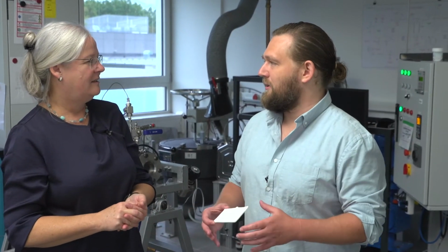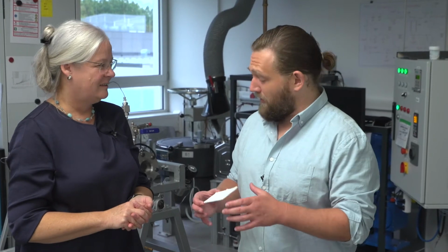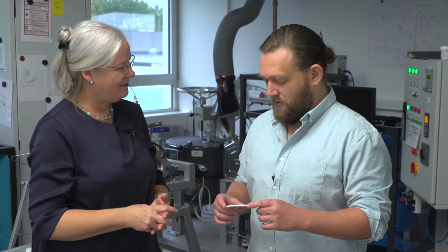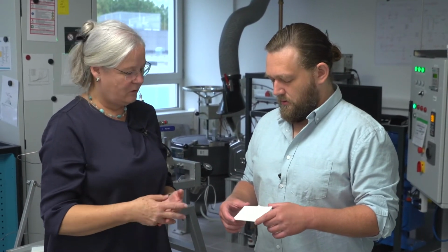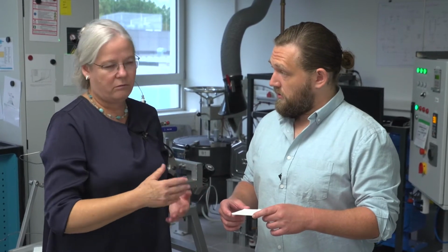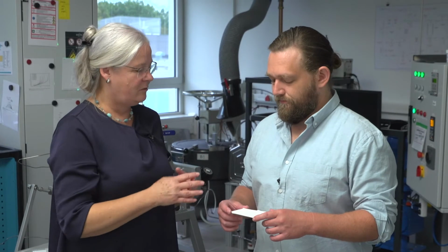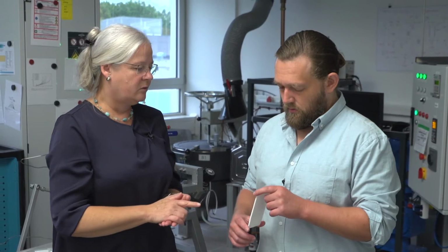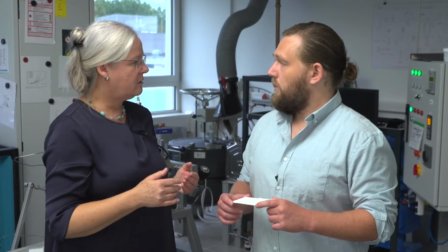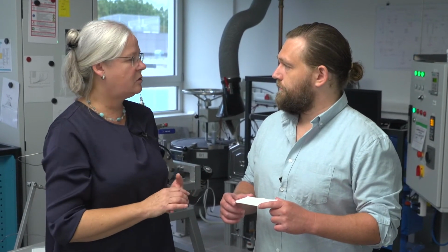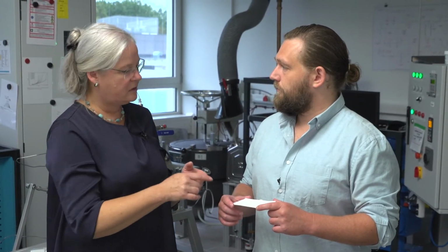A lot of polymer aerogels, in my experience, have higher thermal conductivities, and it's hard to get them as low as silica. But 30 is pretty good. 30 is okay. And we can do it between 2 or maybe 0.5%, but then it is really floppy. We are starting with 2% of cellulose up to 6% or 8%. And we are doing it not with a salt gel technique, but with a salt hydrate melt where you can dissolve the cellulose.